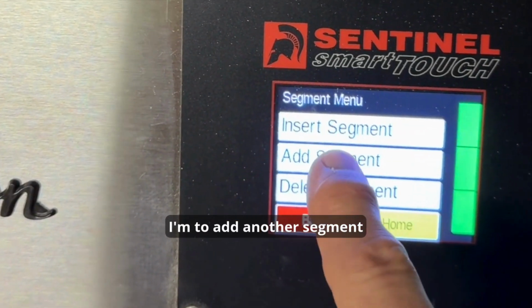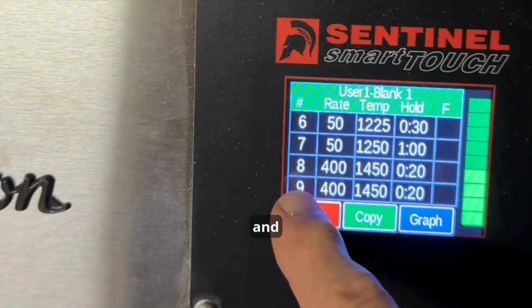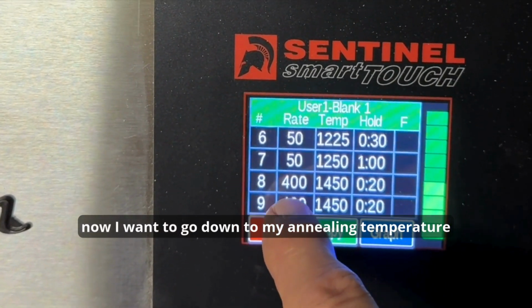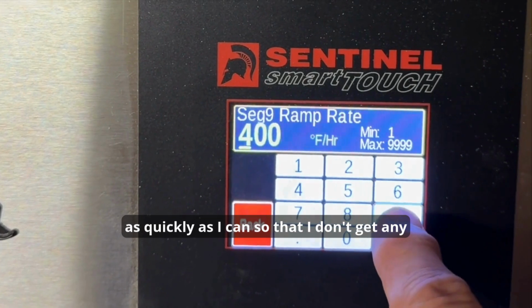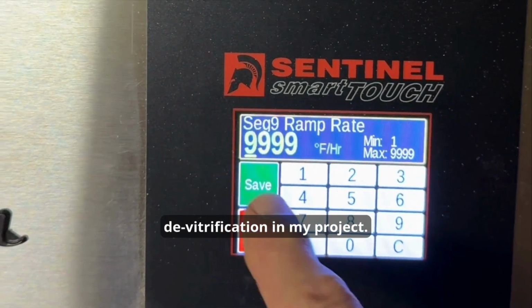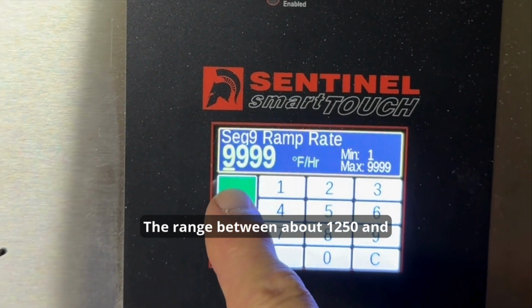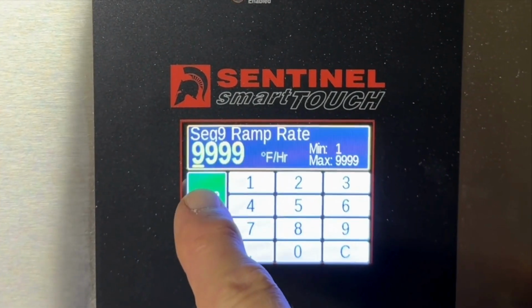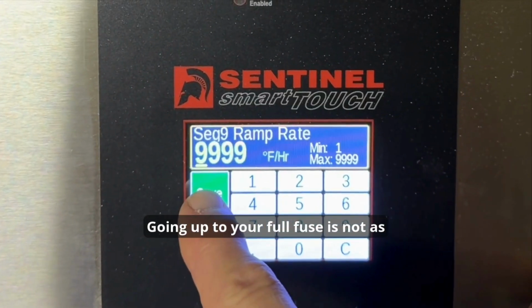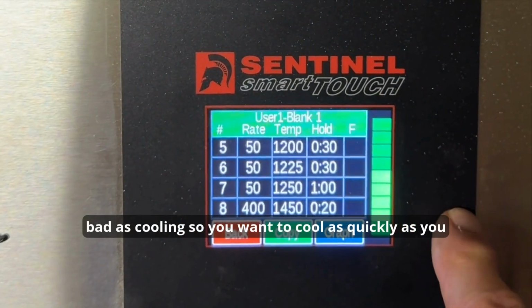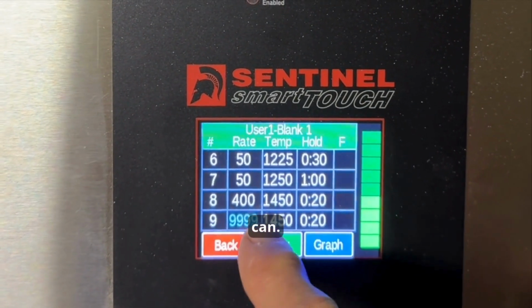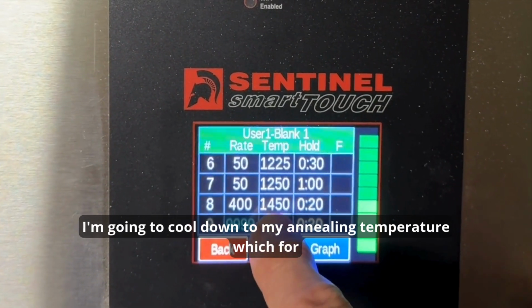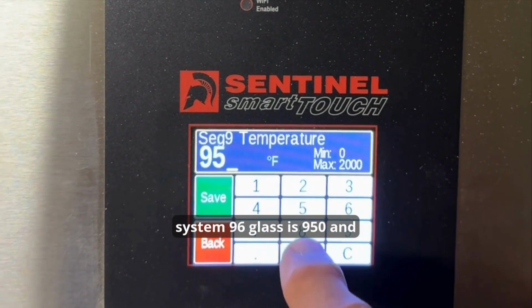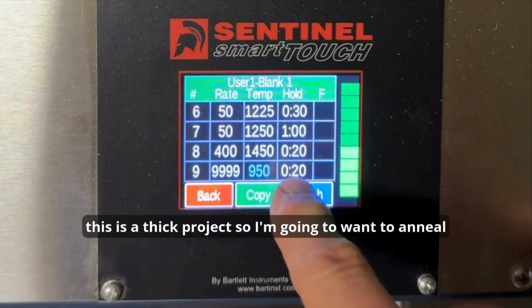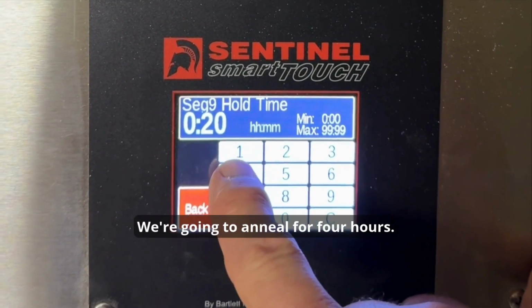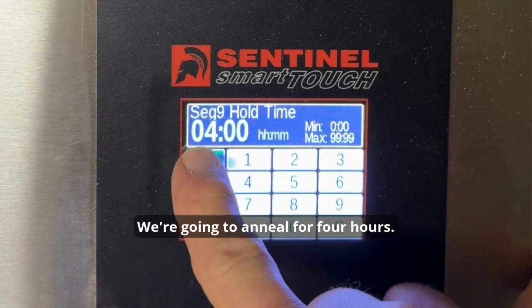I'm going to add another segment. And now I want to go down to my annealing temperature as quickly as I can so that I don't get any devitrification in my project. The range between about 1250 and 1400 is where you get your devitrification. And going up to your full fuse is not as bad as cooling. So you want to cool as quickly as you can. I'm going to cool down to my annealing temperature, which for System 96 glass is 950. And this is a thick project, so I'm going to want to anneal for quite a while. We're going to anneal for 4 hours.